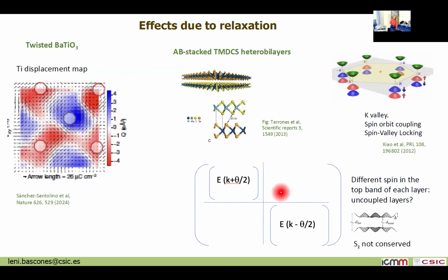And so this type of effects are important to observe this behavior. Another system in which this relaxation is really key is what I was saying before, the transition metal dichalcogenides. If you put them in this AB configuration, if the layers are not buckled, we would not expect to have tunneling because there would be a spin up and a spin down, and so it would be forbidden. In reality, because of this buckling, the spin in the z direction is not well conserved, and so the two layers see each other.